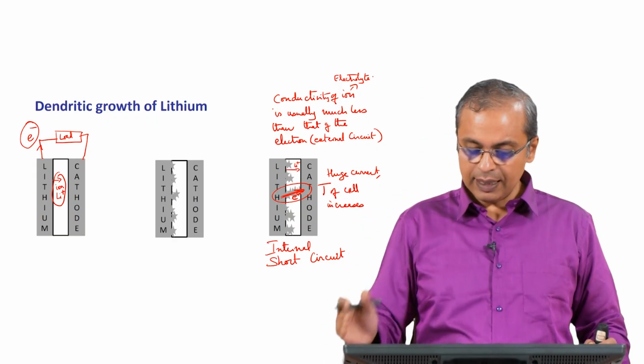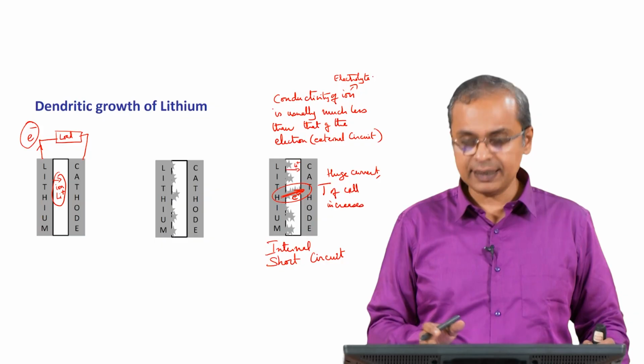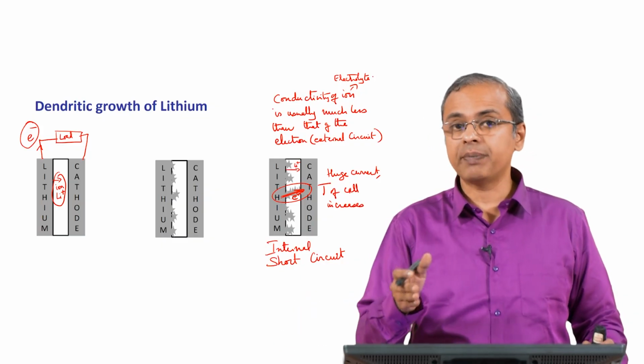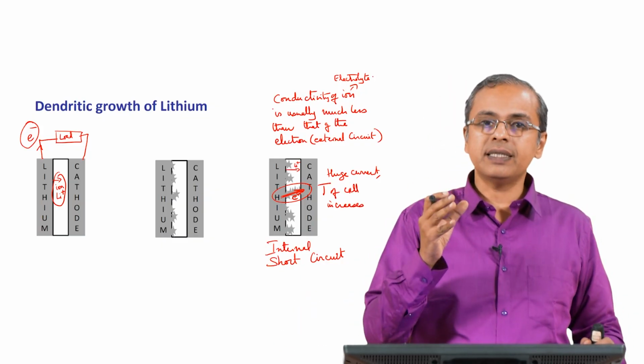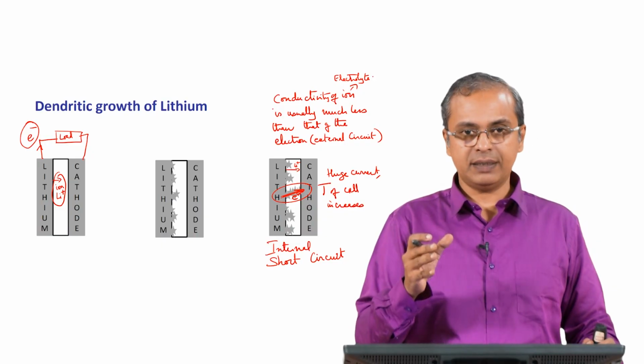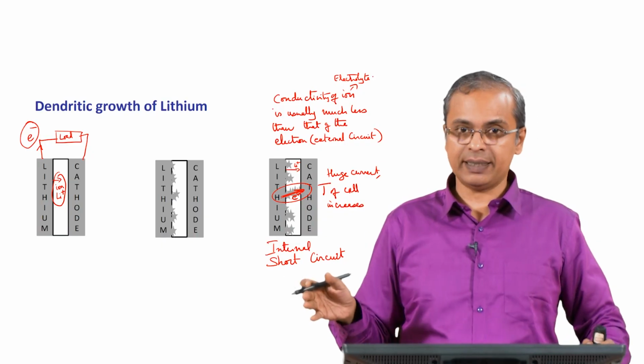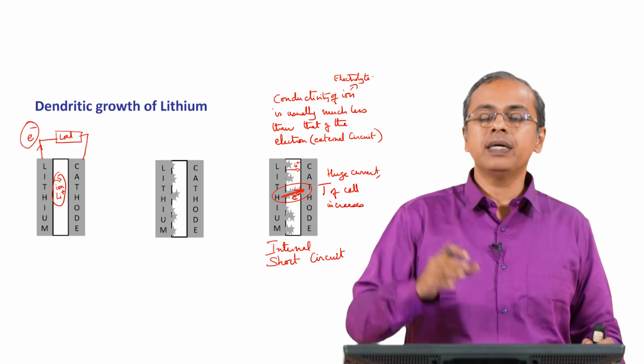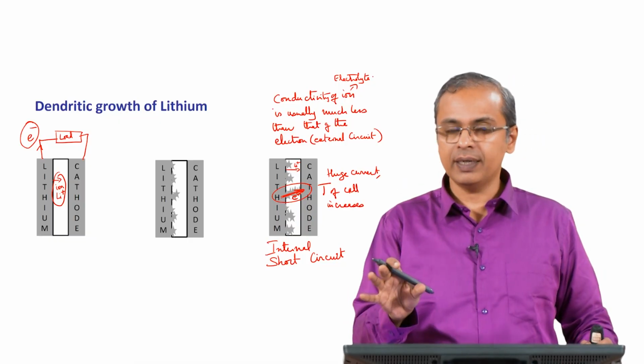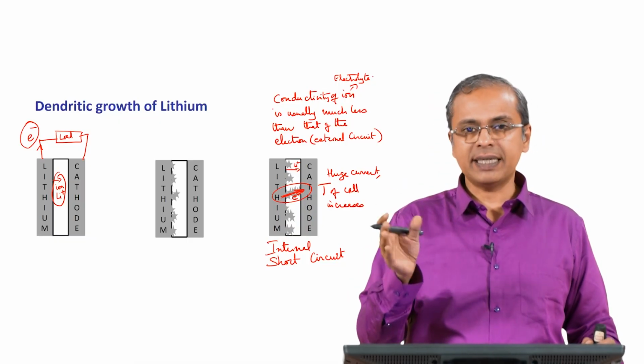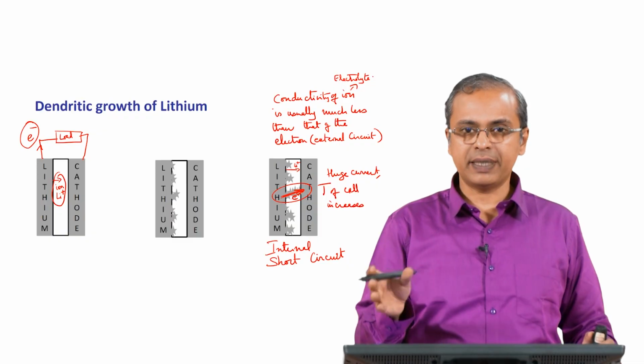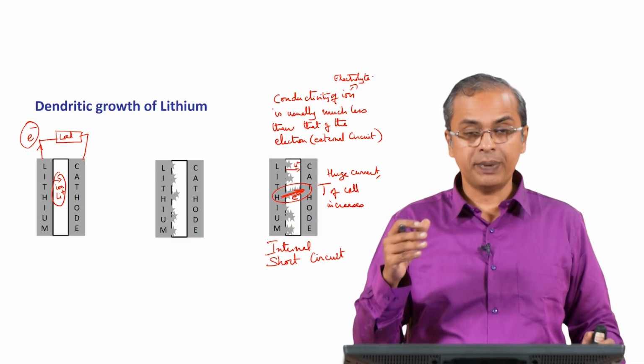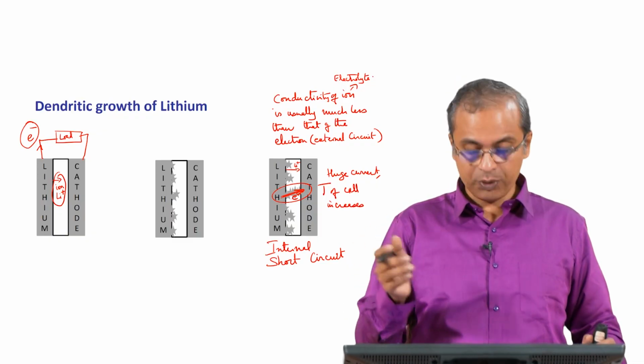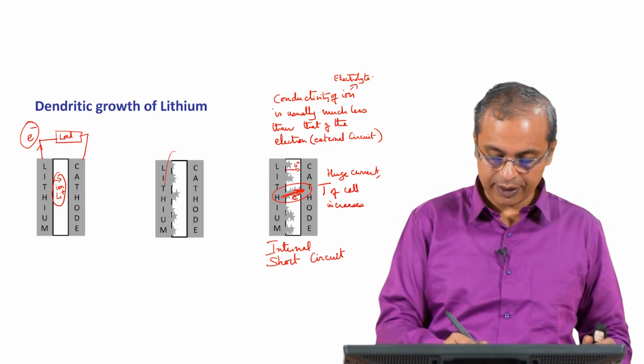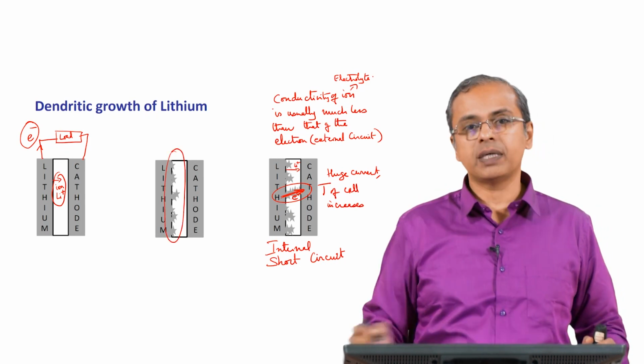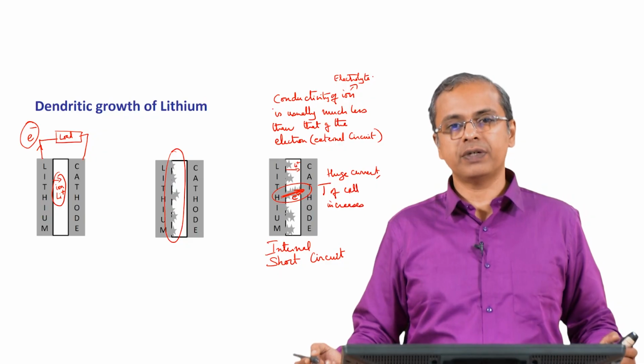So, you must also understand that this happens after a few cycles, it is not happening at the beginning. The first generation lithium rechargeable batteries had this problem: when you buy the battery new, it will be fine and you keep using it for several cycles, 10, 15, 20 cycles, you may not see any problem, it will be working fine, because at that point this is still growing, this has not completed the short circuit, it will keep continuing to function.